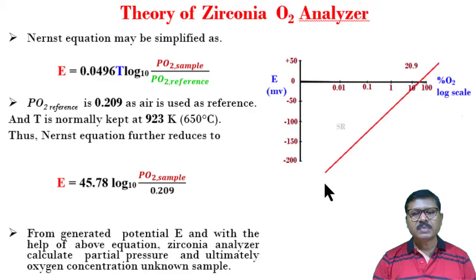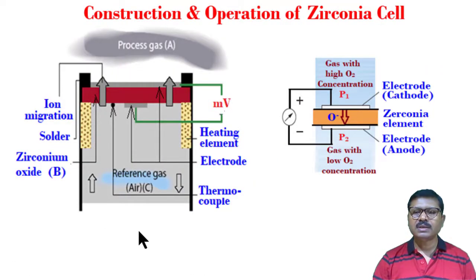So this is the basic theory behind the zirconia oxygen analyzer. Now this is the construction and operation of the zirconia cell. This is the cell, the colored portion is the zirconia element. This is the top electrode, this is the bottom electrode. This is gaseous material on one side, this is gaseous material on the other side. Say this is the high concentration side and this is the low concentration side. From the high concentration side to the low concentration side, there will be a continuous flow of oxygen ions. Because of the presence of these oxygen ions, a potential difference will be developed between these two electrodes, and that difference of potential is the indication of the concentration of the unknown oxygen.